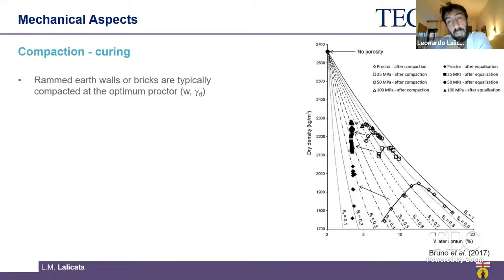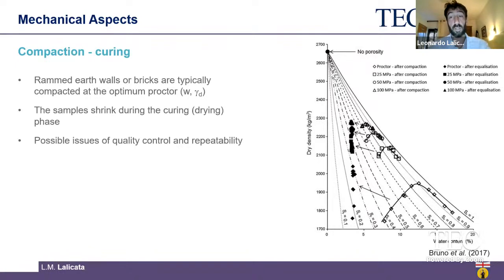After that, as I said, you need to prepare your bricks or your walls, and typically you compact your samples at the optimum water content, which is the amount of water that gives you the highest density at the same compaction energy. But once you have prepared your brick or your wall, you need to wait for it to cure, which means the drying process in which the brick dries, and in this case you can have some shrinking, and this shrinking can induce problems in terms of quality control, repeatability of your results, and then your structure. And this is very important if you want to apply it systematically.